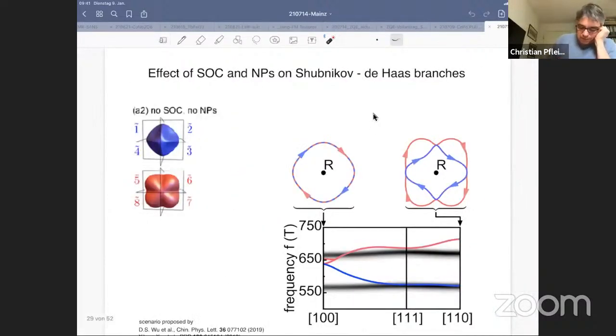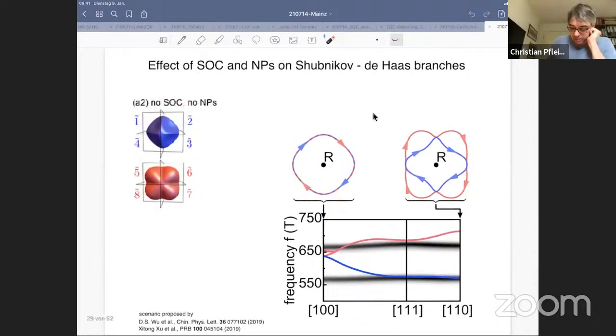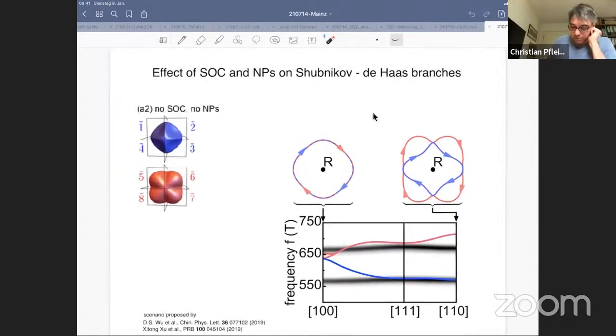Okay, now, what we do is basically look at the orbits around this R point. Right? We say, okay, there are 2 Fermi surfaces. We assume we have no spin-orbit coupling, no nodal planes, and we calculate what kind of orbits we will get. Right? And then we take into account properly the effects of this magnetic breakdown. This will become important in a second. And since the quantum oscillations will show you the largest and the extreme orbits, the largest and the smallest orbits,